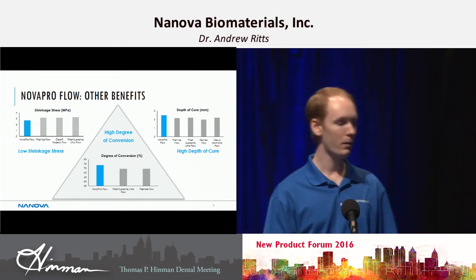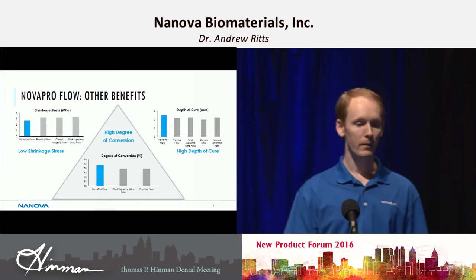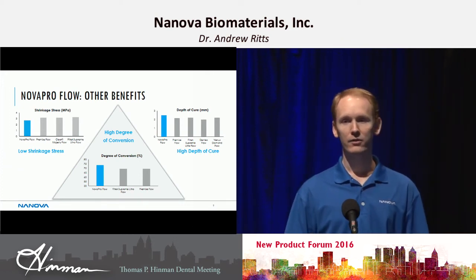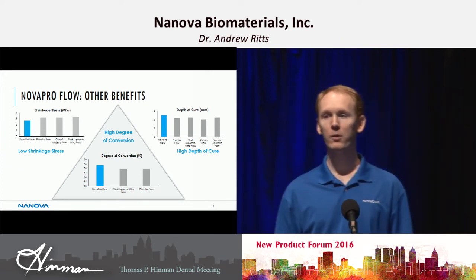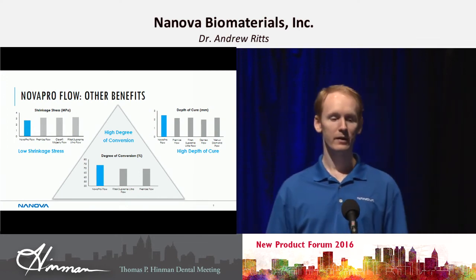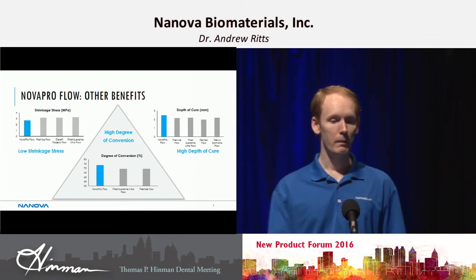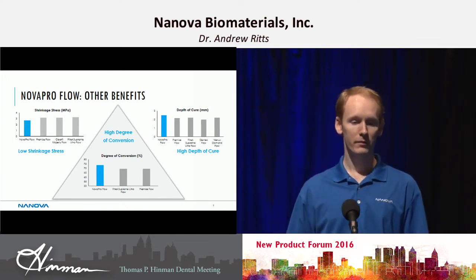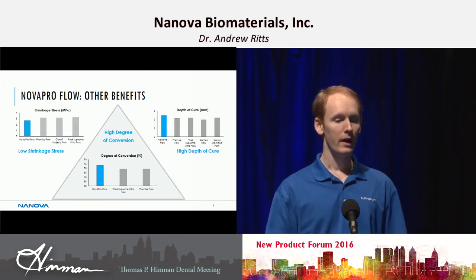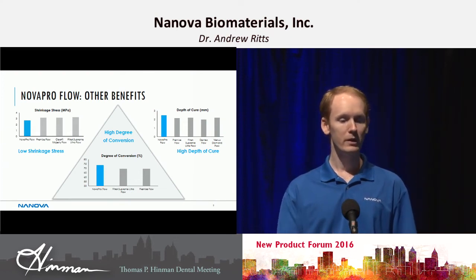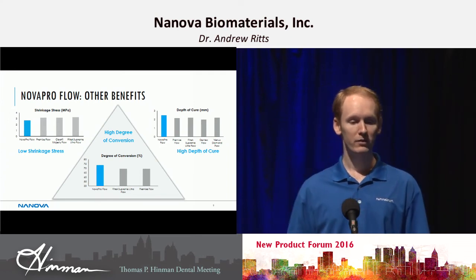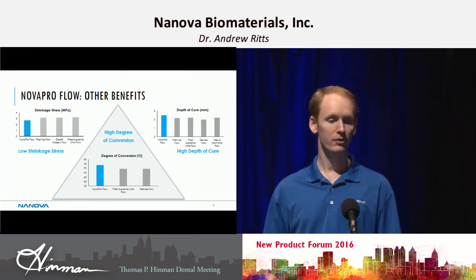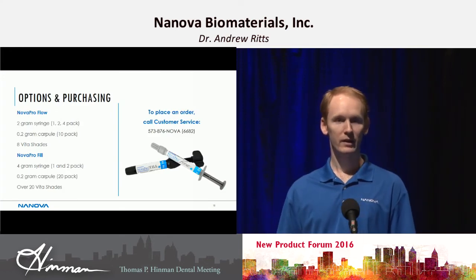Other benefits for our product is we have very low shrinkage stress, and that's very important, especially for a flowable composite, to prevent any problems at the margin. With the depth of cure, we have a very high depth of cure at 2 millimeters and a good degree of conversion as well. Our NovaPro Flow has around 75% degree of conversion with a 20-second cure.